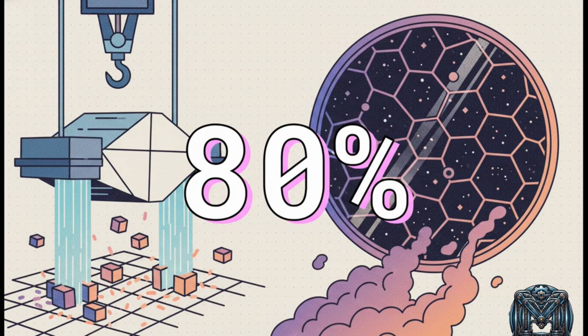Once the glass cools down enough to be handled safely, a massive steel lifting fixture grabs the entire 40-ton structure and turns it completely vertical. Technicians then take high-pressure water and just blast out all 1,700 of those ceramic fiber boxes from the back. What you're left with is a giant mirror that is structurally rock solid, but magically 80% hollow air. They literally wash away 20 tons of mold material in just a couple of weeks. It completely solves the weight problem.